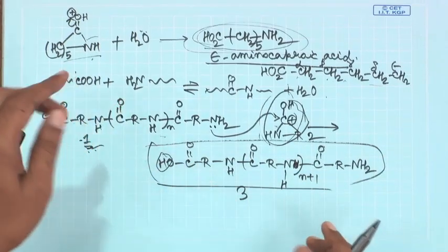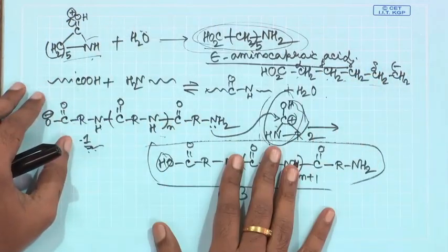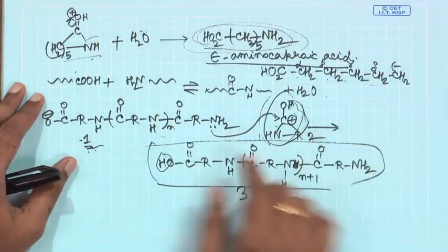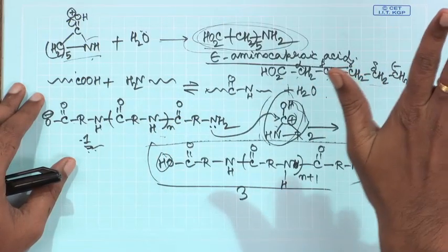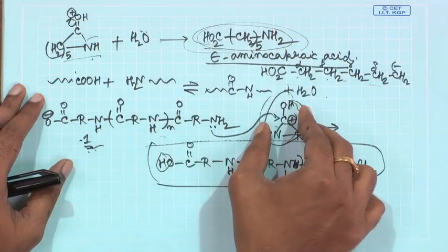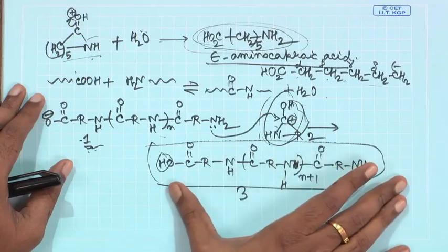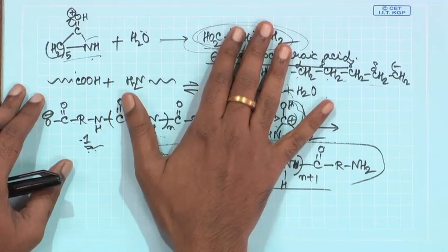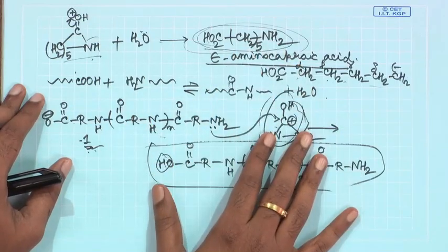So, you can think about it that this polymerization reaction could proceed both ways, either this could self amidate and go on to form a long chain, or at some middle stage whatever self amidated oligomer is there, maybe not a long chain, that can actually open up this, and then through a ring opening polymerization this could elongate. So, both ways, either self amidation could occur or ring opening polymerization could occur in this particular process.